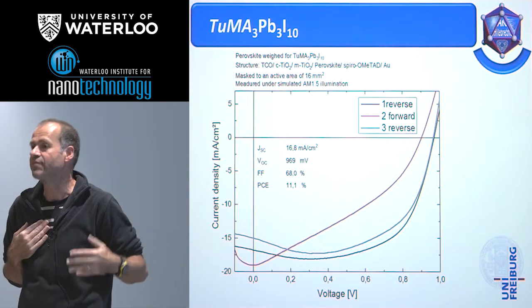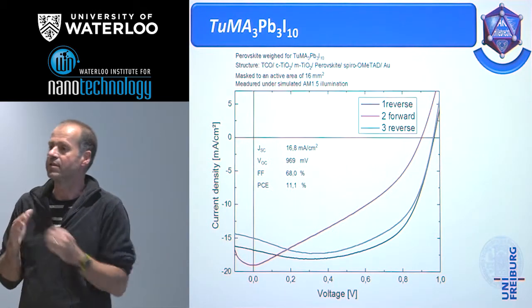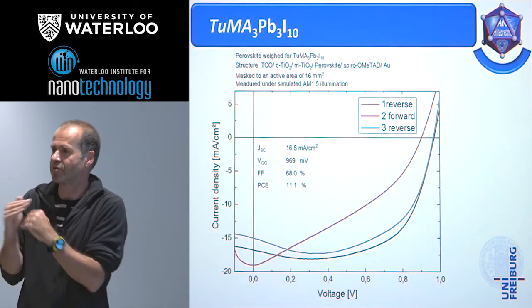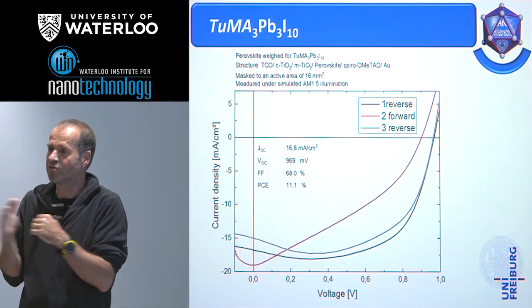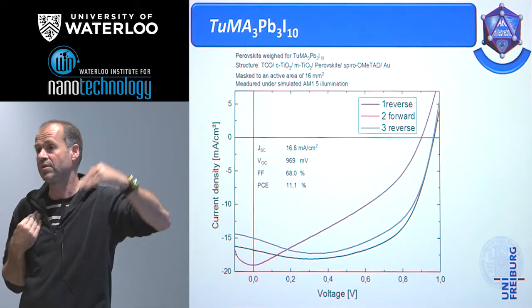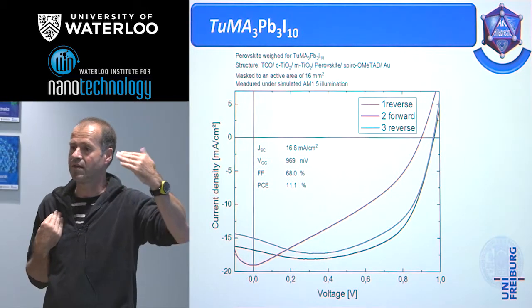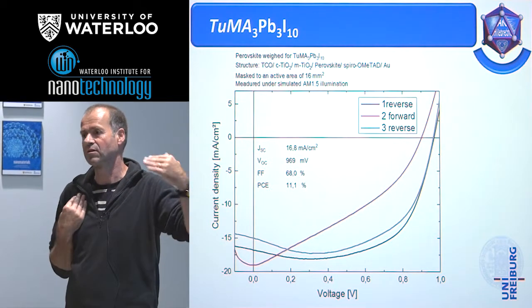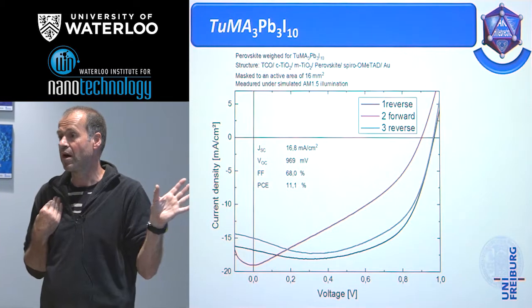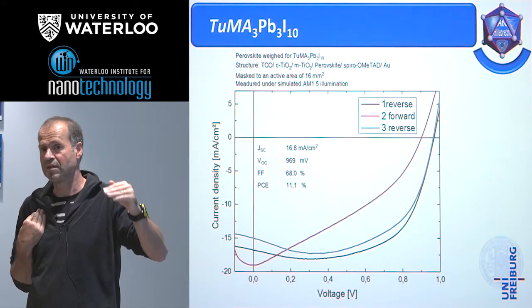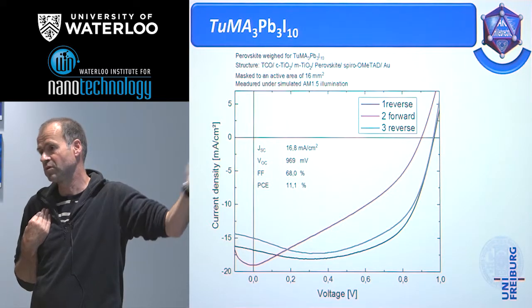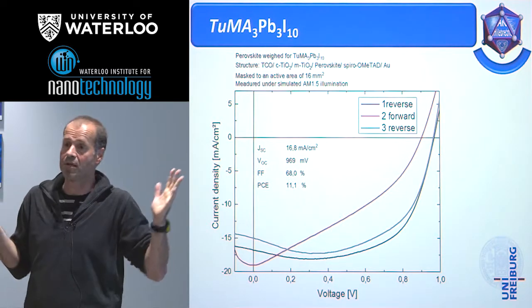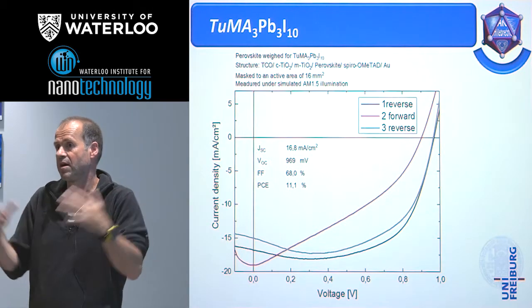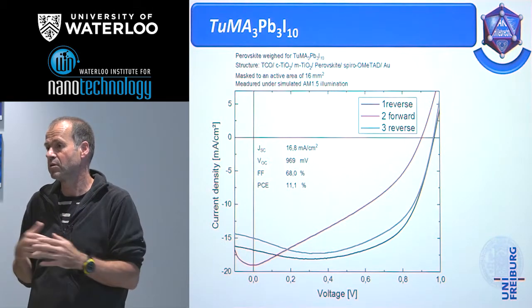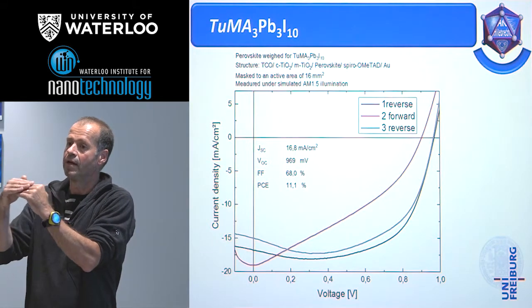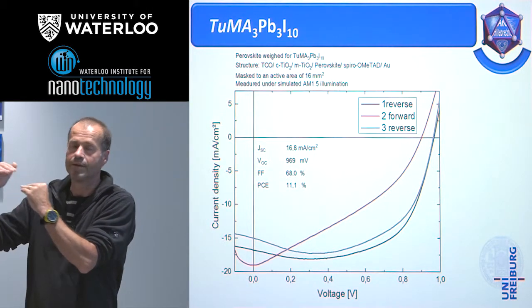Obviously, the excitons have a certain influence, and it seems to be good for the charge separation that you have these layers. But it's not really clear. Nobody knows really how the contact between your dye and the oxide, like titanium oxide or whatever you use, is really made. Also, the contact between the p-conducting layer, which we use, this spiro stuff, and depending on what you use as a material, maybe graphite or carbon nanotubes or what else, there is a difference of the absolute energy.